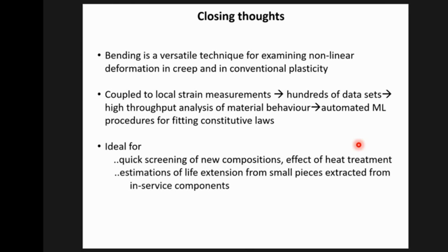So it is really ideal for quickly screening new compositions, the effect of heat treatment, additive manufacturing where you can't make very large samples easily, life extension, and of course things like tension, compression asymmetry. Actually, bending is very nice for doing compression tests. If you look at a lot of compression tests done under uniaxial conditions, the results are very unreproducible. There are all kinds of issues with friction and alignment. This gets rid of all that. Because where you're applying the load and where you're applying the deformation are two completely different places.